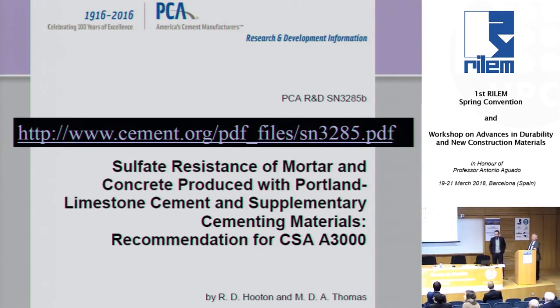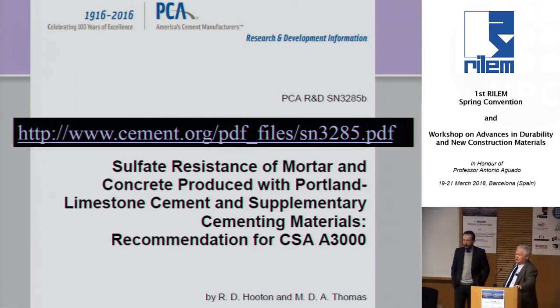Doug, I understand why you use the test method, but you didn't quite explain why you were doing prescriptive requirements. Can you replace them with some performance requirements? We had some prescriptive requirements. When we first did this, the people in Western Canada in the ready-mix industry were very nervous about allowing this type of cement in exposures where they knew they had severe sulfate problems. And if they don't address sulfate resistance there, the concrete doesn't last 5 years.